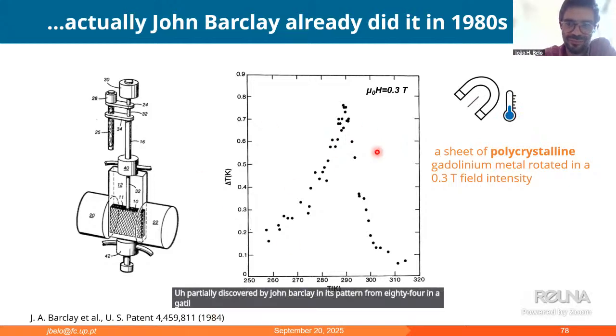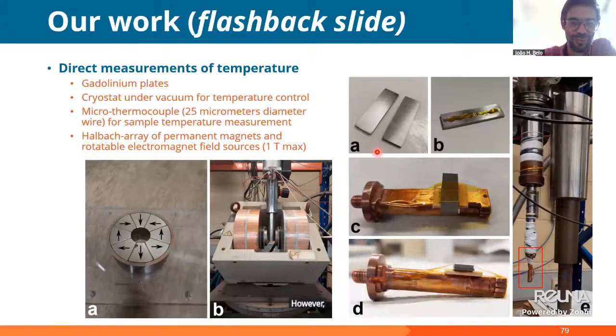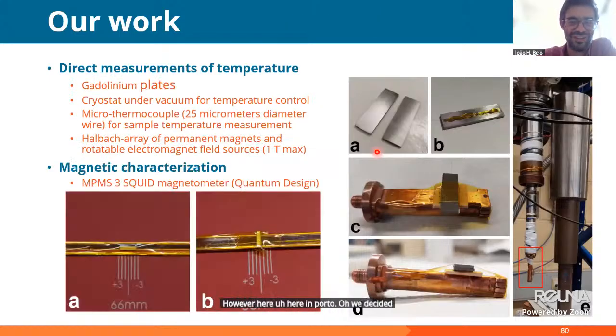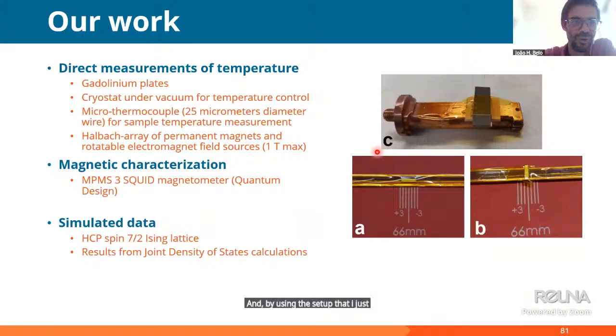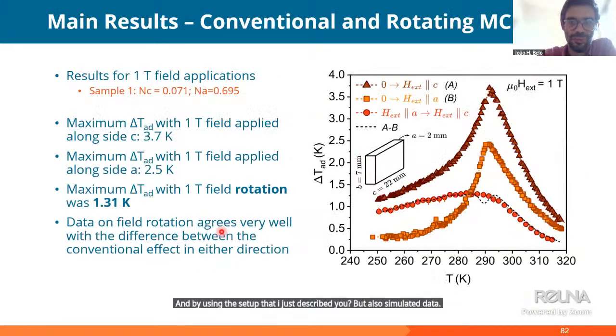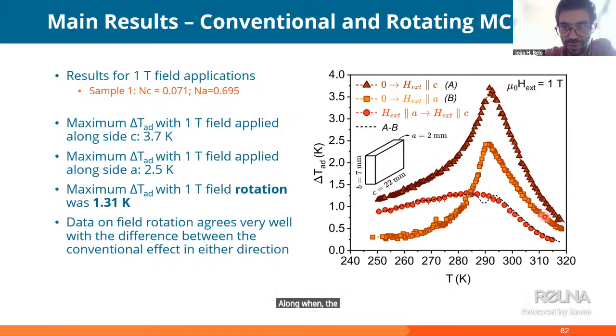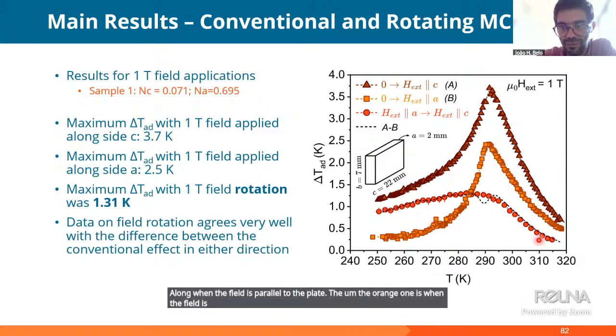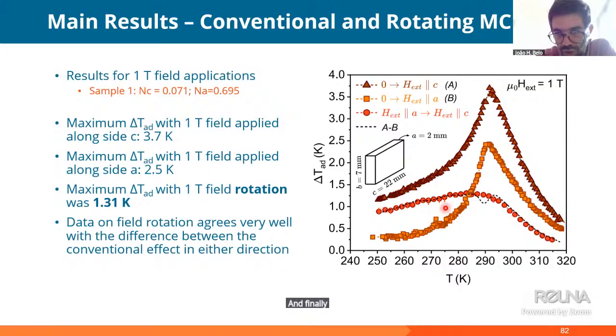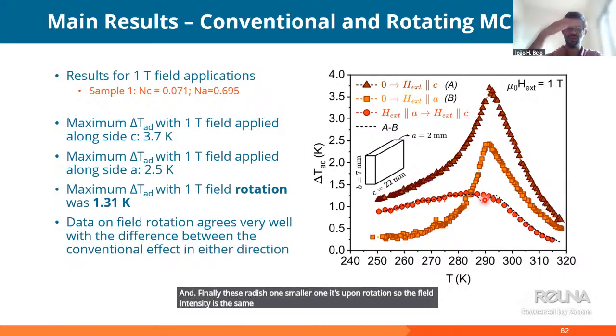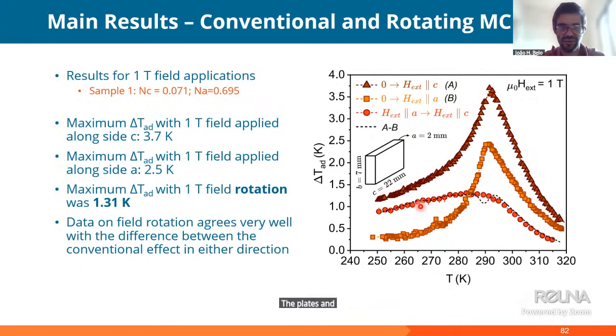in a gadolinium plate. However, here in Porto, we decided to investigate this further, and by using the setup that I just described to you, but also simulated data, we are able to measure the delta T under a 1 Tesla field intensity, conventionally when the field is parallel to the plate. The orange one is when the field is perpendicular to the plate. And finally, this reddish, smaller one is upon rotation. So the field intensity is the same. We just rotate the plate and we get a delta T.